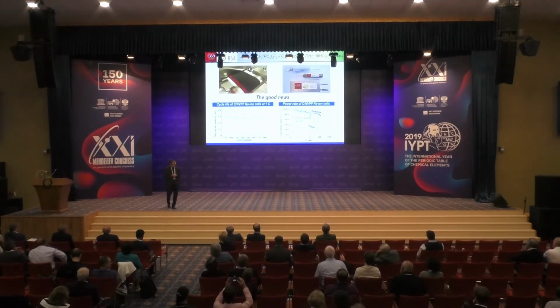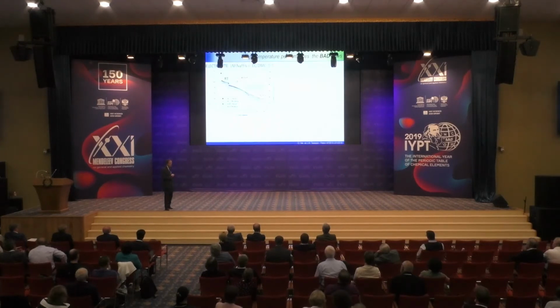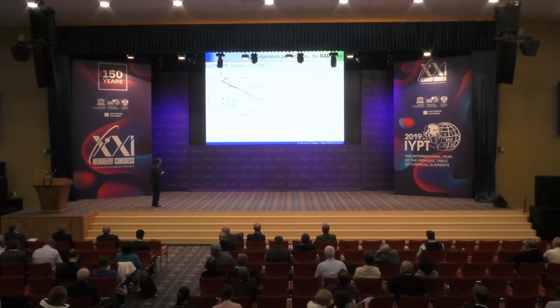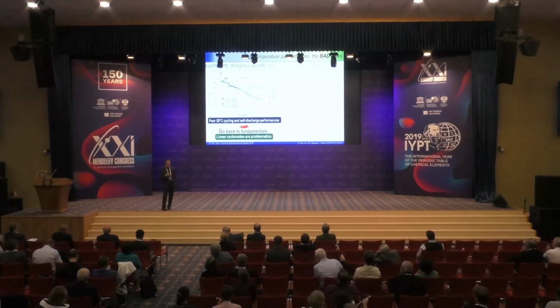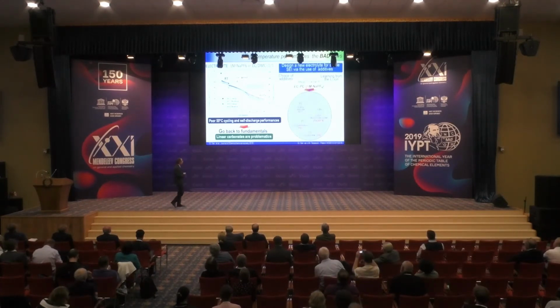So it was good news, but it didn't last too long, because we have some bad news: when we want, of course, to use these batteries at high temperature, and when I mean high temperature, it's not too high, 55 degrees C, you can see that now we have a drastic capacity decay and huge cell discharge. So in this case, we need to go back to fundamentals, try to understand why it was happening, and this was due to one component of the electrolyte, which was a linear carbonate, DMC, and we need to replace it.